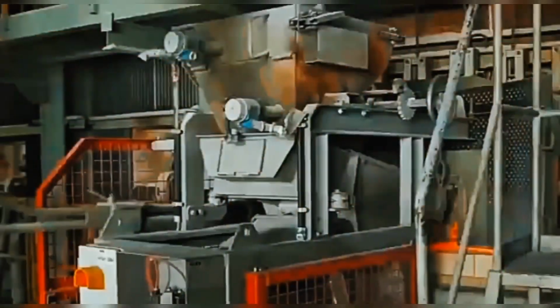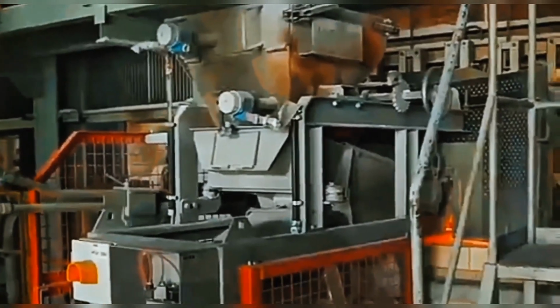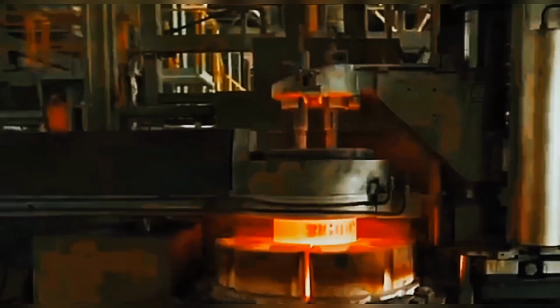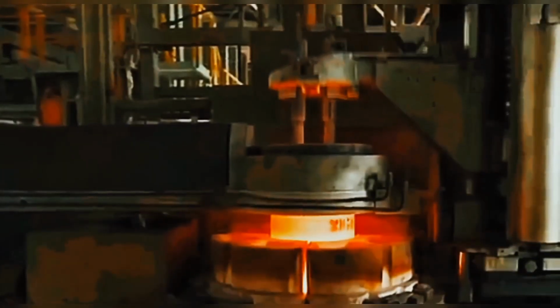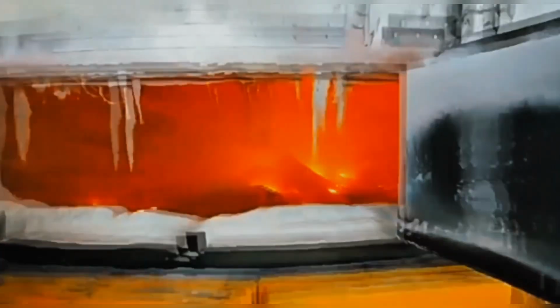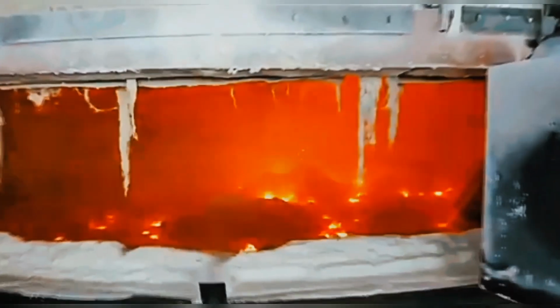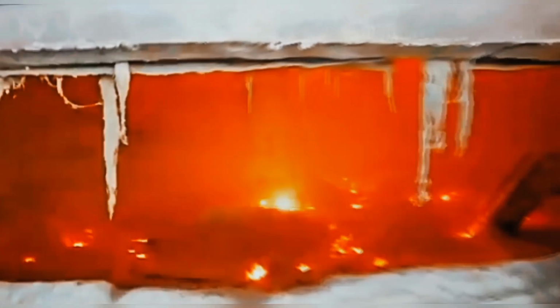What actually happens in the glass? Melting reactions. Carbonates decompose, releasing CO2. Grains dissolve, and the network forms. Cullet accelerates these kinetics. This is the most energy-intensive part of the whole plant. Refining. Tiny bubbles must be removed. A traditional aid is sodium sulfate. At high temperature, it releases sulfur dioxide and oxygen, which first grow bubbles so they coalesce and rise faster. Then, as the melt cools, gas solubility increases and bubbles shrink or dissolve out.